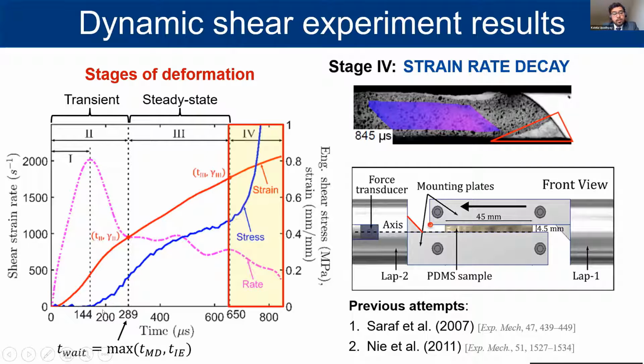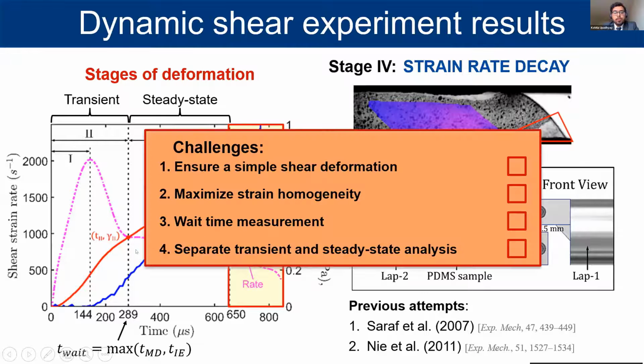As I said previously in my introduction, these tests are very uncommon and there have been only two previous attempts at creating SHPB-based dynamic shear tests for soft materials. And none of those previous experiments could present the actual steady state material response because of the inability of those experiments to measure the wait time. So if we look at our challenges box again, we just successfully made the wait time measurement and now we can separately analyze the two different stages of deformation.